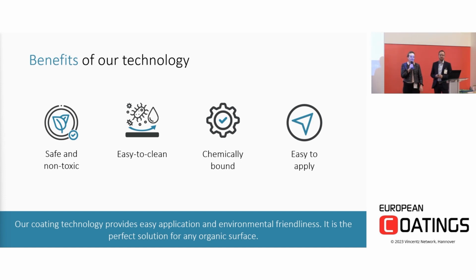One of the most important properties of our coating is probably that we are non-toxic and non-biocidal, which means it's a very safe technology to use, and it's not subject to the EU regulation of biocides. How does it work? It's based on a purely physical effect. We hydrophilize the surface, which impedes the attachment of bacteria to the surface. That means if you don't do anything with your surface, bacteria can grow on our coating. They are not killed by the coating. It's non-toxic. But as soon as you wash the surface, all of the bacteria and the biofilm is removed from the surface. So it's an easy-to-clean solution.